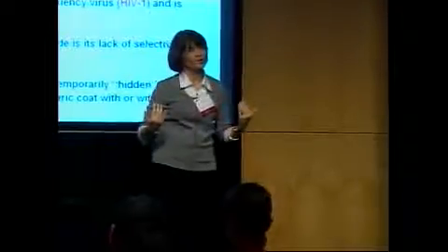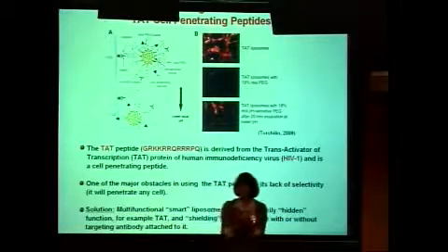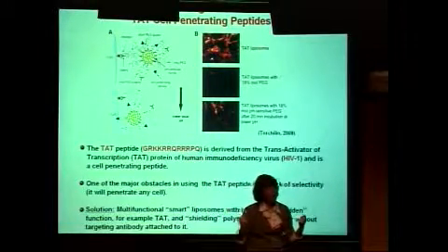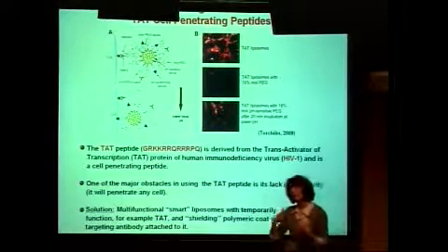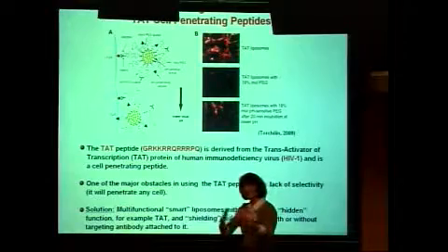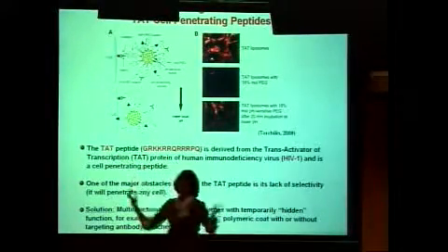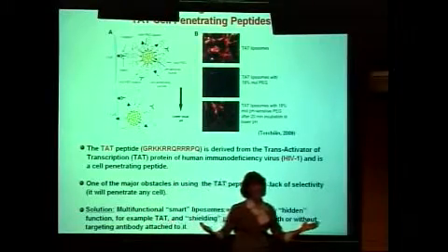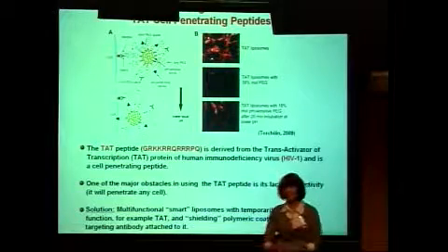But then when it came to the vicinity of the tumor, which has a lower pH compared to the rest of the body, these polymer chains were conjugated to the nanoparticle with bonds that you can basically hydrolyze or break when they are exposed to low pH. So as soon as the nanoparticles came close to the tumor area, the pH was lower, the bonds were broken and hydrolyzed, and now the cell-penetrating peptide is exposed. It can do the job, and the nanoparticle can go inside the cancer cell.